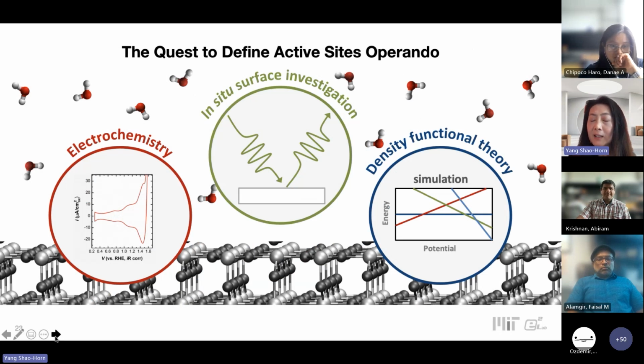So one can say that these would be correlations, right? Correlation we know is not causation. So the question will be, can we learn more about what the active sites are and how the active sites may turn over as a function of voltage or operating conditions? And in this regard, to probe the elementary reaction processes and define what the active sites might be, we leverage electrochemistry of single crystals as well as in situ characterization, utilizing synchrotron coupled with density functional theory.